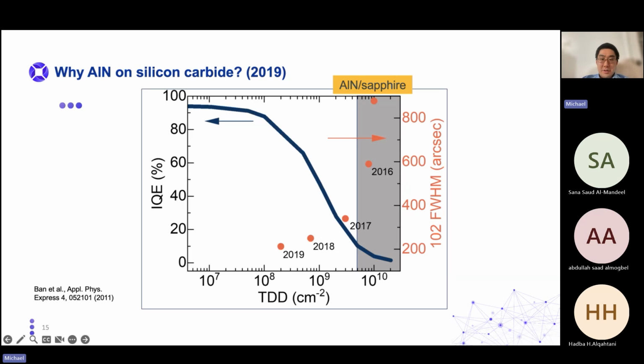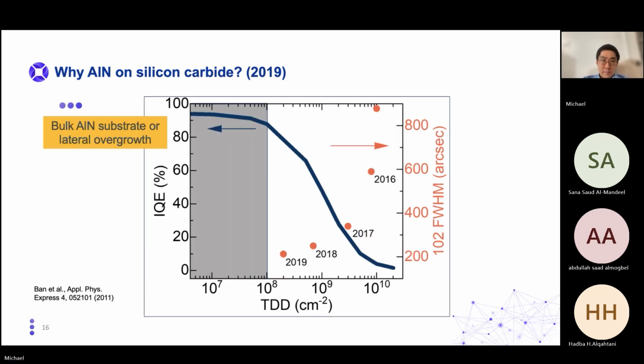So the reason is that in 2019, aluminum nitride on sapphire was very defective. So TDD is a measure of the defect density, threading dislocation density. And aluminum nitride on sapphire back in 2019 and earlier was commercially in the high 10 to the 9 to 10 to the 10. And it was very difficult to get good samples of aluminum nitride on sapphire, mostly due to the large lattice mismatch of approximately 13% between the aluminum nitride and sapphire. Over here on the low side, which you would prefer in terms of defect density, bulk aluminum nitride or lateral overgrowth methods is used to achieve this, but both of these are extremely expensive even now, and are not commercially viable technologies, even now in 2025, and much less in 2019.